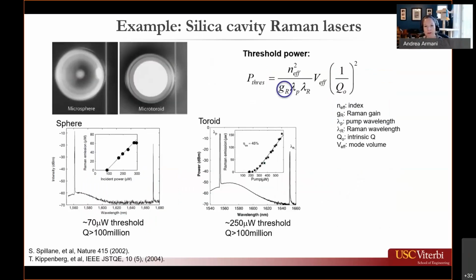So a brief overview of some of the past work that has been done using silica cavity Raman lasers. Previously, researchers have shown that using a silica cavity, whether it's a microsphere or a microtoroid, if you put in very low amounts of power, in the microwatt range, but you have a high enough Q, you're able to get Raman with very low thresholds. And this is notable because silica has a very low Raman gain, but you're able to overcome this low Raman gain because of that very high quality factor. And these are just two examples showing the single mode Raman emissions as well as the threshold from both devices.